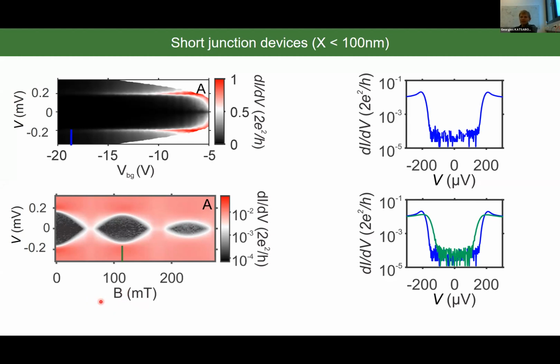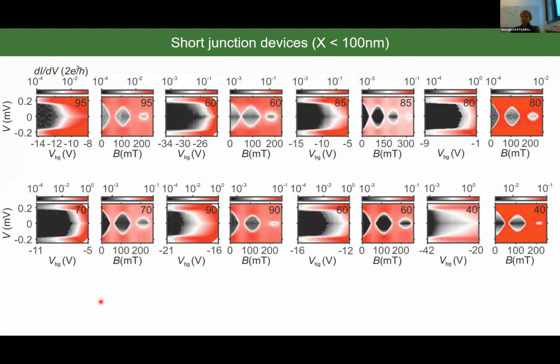We have investigated many short junction devices, and here I show you an overview of 8 other devices. In the top right of each device, I'm giving the dimension of X, of the tunnel barrier. And on the left side, you can see the measurement we have done in order to find the regime for which we will be doing tunneling spectroscopy. And on the right side, we have fixed our backgate voltage and we are sweeping bias versus magnetic field. What you can see is that in none of the measurements we see any zero bias peak. So we have no indication of Majorana zero modes.